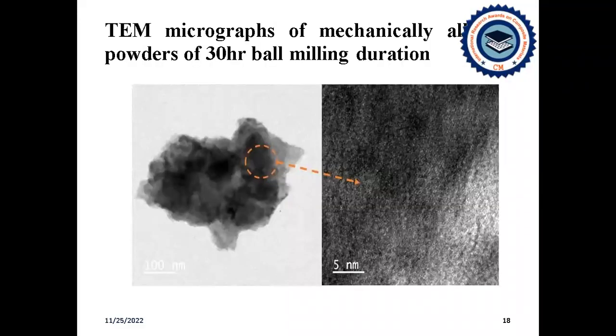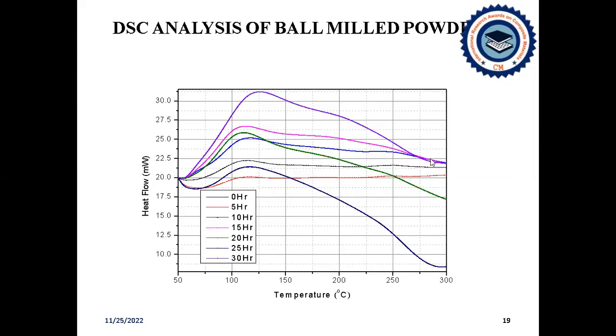This is the TEM micrograph of mechanically alloyed powders of 30-hour ball milling duration. You can see the small minute particles that are present, which indicates that nano size particles are present in the ball milled powder sample.